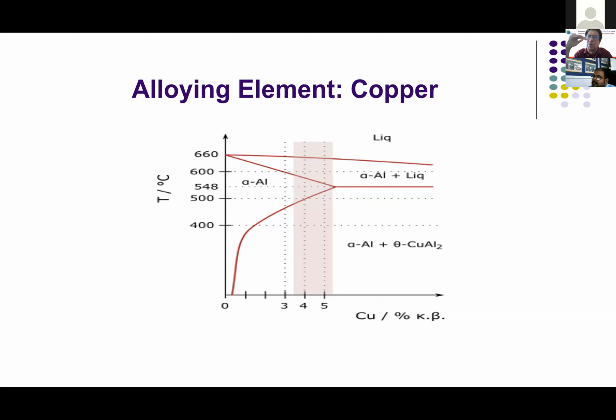And when you cool down, it precipitates again. By controlled dissolving and reprecipitating of the copper, we achieve an extremely high tensile strength and also very good elongation. This phenomenon is widely used in heat treatment. Silicon does not have this property, whereas copper has it, and magnesium.